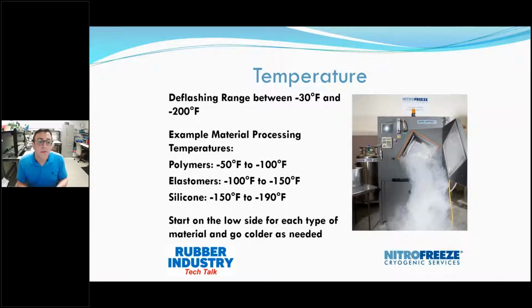So in terms of what temperatures we process parts at, we're between -30 and -200. To give you examples of ranges, this is where you should run your parts. I always recommend starting on the low side to see if you're getting a result. Usually for polymers it's -50 degrees Fahrenheit to -100 degrees Fahrenheit. We could run, let's just say, a nylon at -70 degrees Fahrenheit, while a PEEK might be run at -60 degrees Fahrenheit. So I always recommend starting on the lower side.